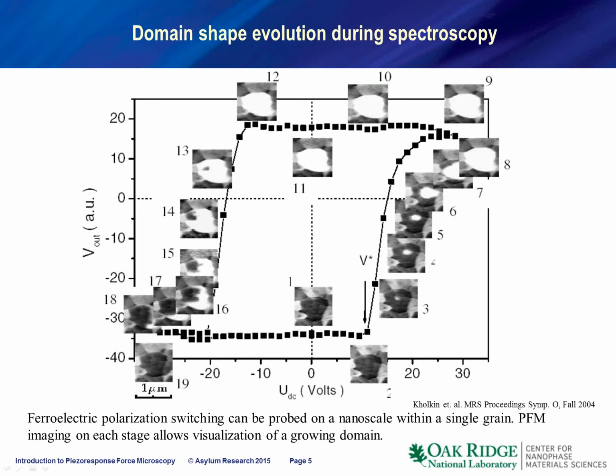However, what you can also see from this image is that the domain formation is much more complex than represented by a single hysteresis loop. The domain shape is absolutely not cylindrical. It forms protuberances, as you can clearly see in frames 5 and 6. It forms protuberances in different directions, as you can see in 13 and 14. So the process of switching is complicated and strongly affected by the presence of other grains, disorder, and so on and so forth. So the question is, how can we study the switching process in more detail?